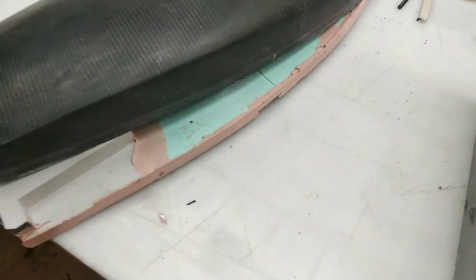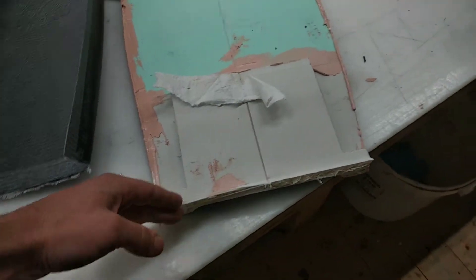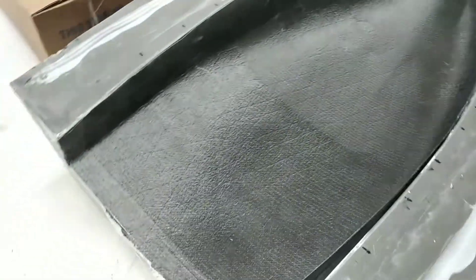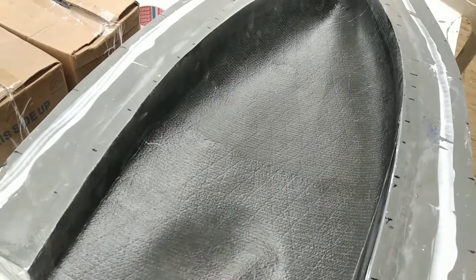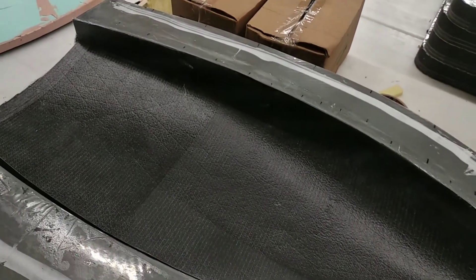When I place it down it's going to be flat and chamfered, and pretty easy to fit the hull on top. That's the whole reason why I did the extra step to build this extra surface. This surface will get some peel ply so I will not have any sanding to do, and I will run a bead of glue round about here. For the transom I still don't know if I want to keep it open and glue it afterwards or attach it to the mold — I think I will keep it open. These white marks here are some tiny little cracks which came from de-molding because the hull was so light that I needed to peel it basically out of the mold. I used a chemical release agent which was pretty good but I didn't let it cure long enough before de-molding, so that's something to address for the next one.